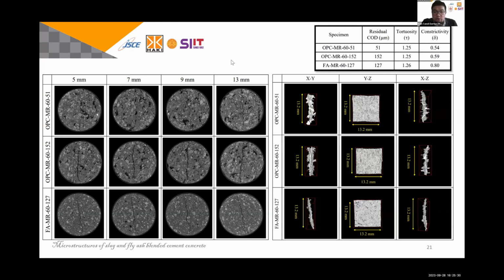And then after thresholding, we will have the crack geometry here. We will have a 3D of the crack. Here, as you can see, we evaluate tortuosity, I mean the straightness level, and finally constrictivity. Constrictivity means the variation of crack width. For all specimens, the crack geometry is similar, around 1.2. For tortuosity, the straightness, a value of 1 means straight. If higher than 1, it means you have some tortuosity. And then constrictivity, a value of 1 means uniform crack width, but lower than 1 means you have a variation in crack width.